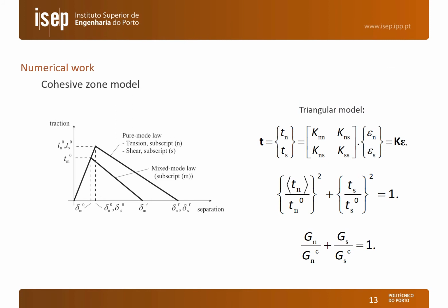As I said before, we use a triangular cohesive zone model, and these are the main equations that depict the behavior of this triangular model law. We are considering a linear elastic behavior up to the cohesive strengths Tn0 and Ts0, cohesive strength in tension and shear respectively. We consider the quadratic stress criterion for damage initiation based on the current stresses, and a linear energetic criterion for damage propagation as seen in the last equation of this slide.